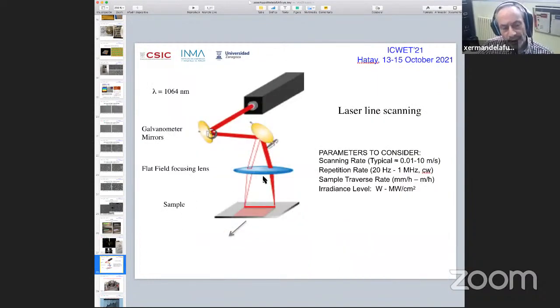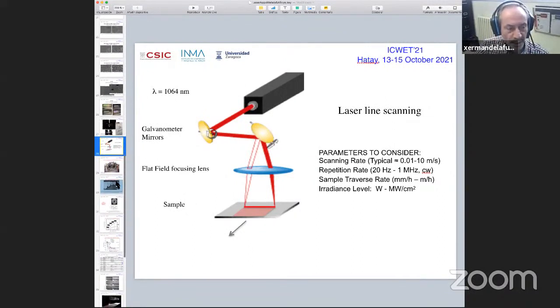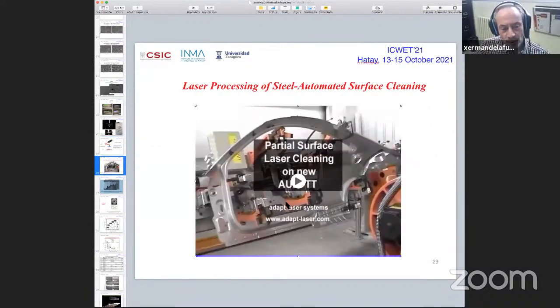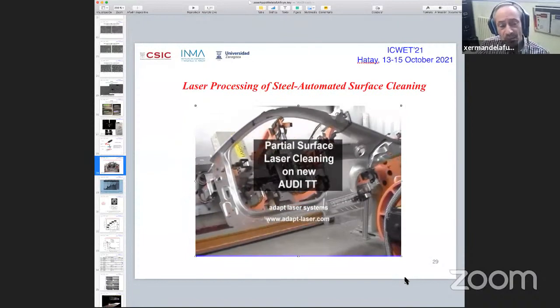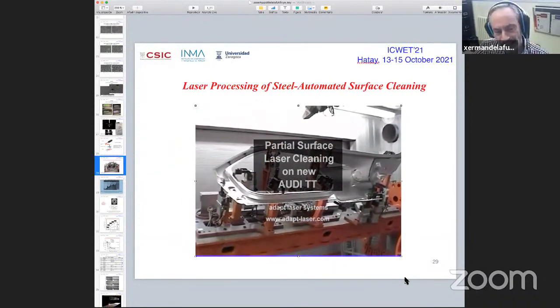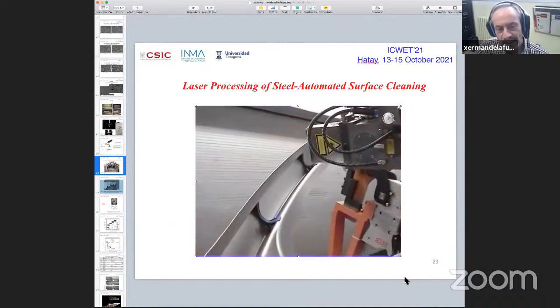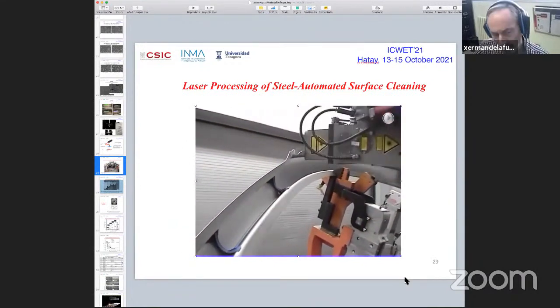To work in large areas, laser beam scanning is not so advantageous. So we developed what we call laser line scanning that people are using now, where we do a beam scan and we move the sample at a constant rate, so we can do any of these operations that you saw before in very large areas and with very good control. Of course, this is also done in industry. You could call this a laser line scan, or an automated laser line scan. As you can see, this is for cleaning. Now it's not for structuring, but rather cleaning.